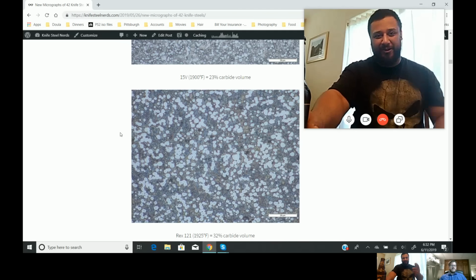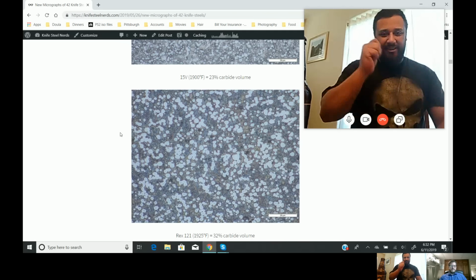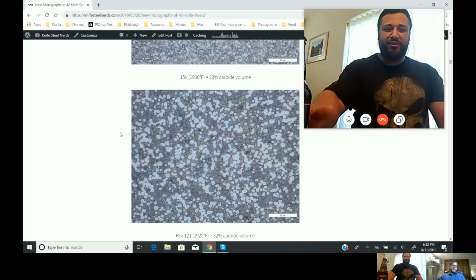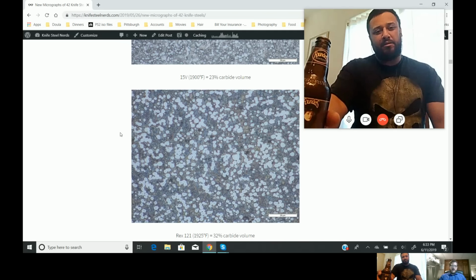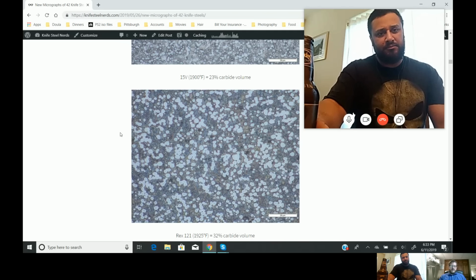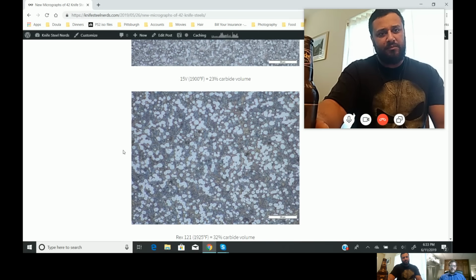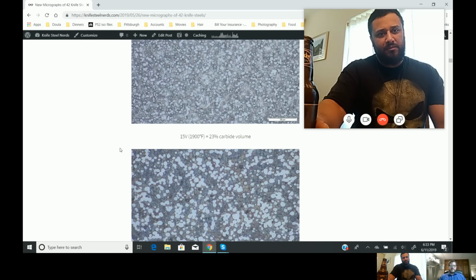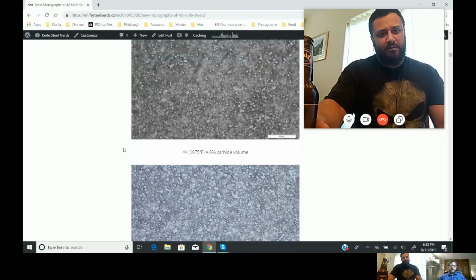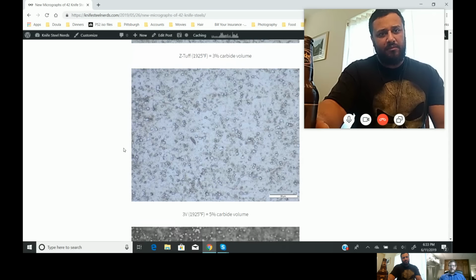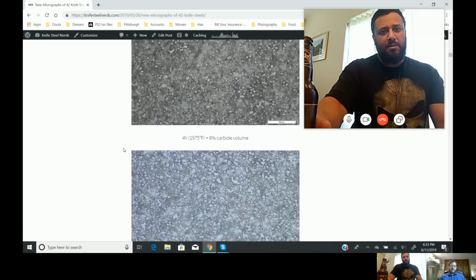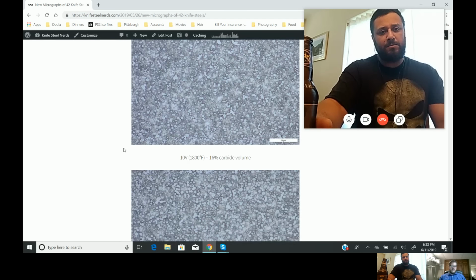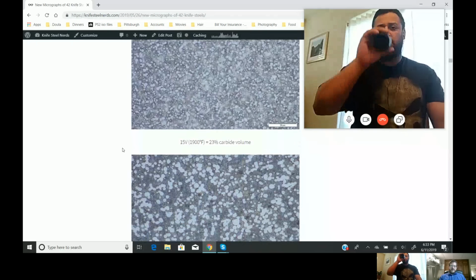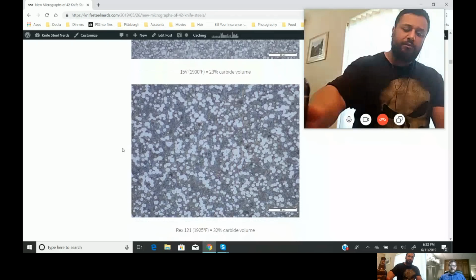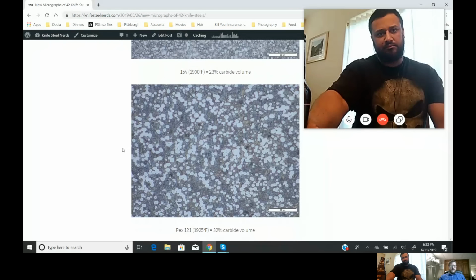Because that Rex 121, I mean, it's got the most. That's the best, but not always. And powder metallurgy helps to keep them small. But you can tell even that Rex 121 with over 30% carbide, they're bigger than the steels with 20% carbide. And those carbides are bigger than the steel with 5% carbide in it. So they get bigger and you get more of them. And even though powder metallurgy makes them smaller, it's not going to make a high wear resistant steel just as tough as Z-Tuff. It's not possible with our current technology.